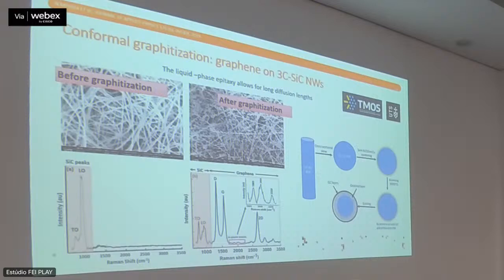And there are some very interesting things that we discovered by looking into these nanowires. But the thing is that you don't need to coat everything around, because we work with the liquid phase. And in the liquid phase, everything will start flowing at really high temperature. So all of the catalysts will flow around and cover all of the walls of the silicon carbide. And this is shown within.